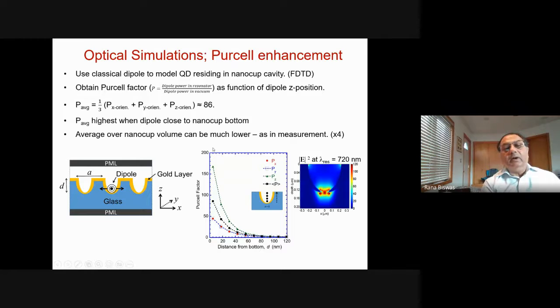And when you average over the entire nanocup volume, the Purcell factor can be much lower, as in the experiment, and approaching the factor of 4. So it's highest when the dipole is close to the nanocup bottom, but quite a bit lower when you go further out. And you're just sitting further away from the field maximum here.